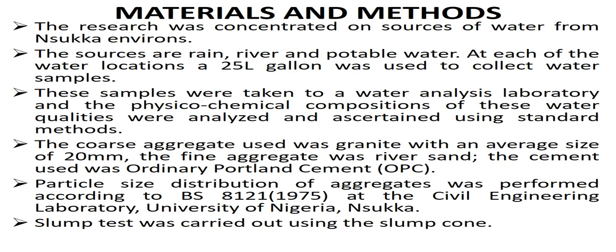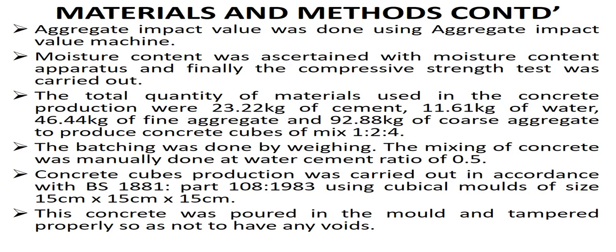The coarse aggregate used was granite with an average size of 20 mm. The fine aggregate was river sand. The cement was ordinary Portland cement. Particle size distribution of aggregates was performed according to BS 8121 1975 at the Civil Engineering Laboratory, University of Nigeria, Nsukka. Slump test was carried out using the slump cone. Aggregate impact value was done using aggregate impact value machine. Moisture content was ascertained with moisture content apparatus, and finally the compressive strength test was carried out.